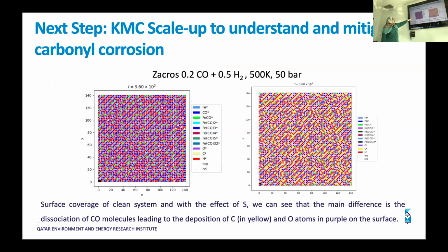So you see here the surface coverage without accounting for sulfur, and here we're accounting for sulfur. You can see that at the end, if you look at the surface from the top, these are all the species that we have identified.